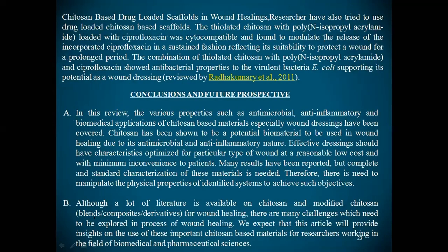The chitosan based drug loaded scaffolds in wound healing. Thiolated chitosan with poly N-isopropylacrylamide loaded with ciprofloxacin is suitable for protecting the wound for a prolonged period. This combination of thiolated chitosan with poly N-isopropylacrylamide and ciprofloxacin shows antibacterial properties against the well-known bacterium E. coli.